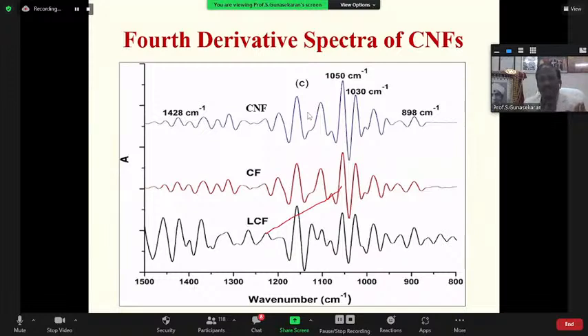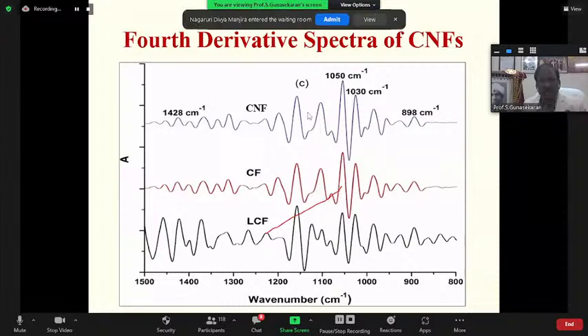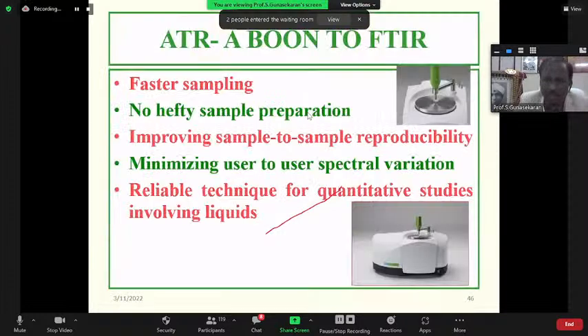Crystal structure is here. With that material, we have fabricated a material which can be used as a filter in water purification. This is done also. The nanocellulose fiber is important. We can synthesize a cellulose nanofiber from paper by using some chemical process. That's all. So in this way, we can use our ATR technique in different areas. Faster sampling, no sample preparation, improving sample to sample reproducibility, minimizing user to user spectral variation, reliable technique for quantitative studies involving liquids.